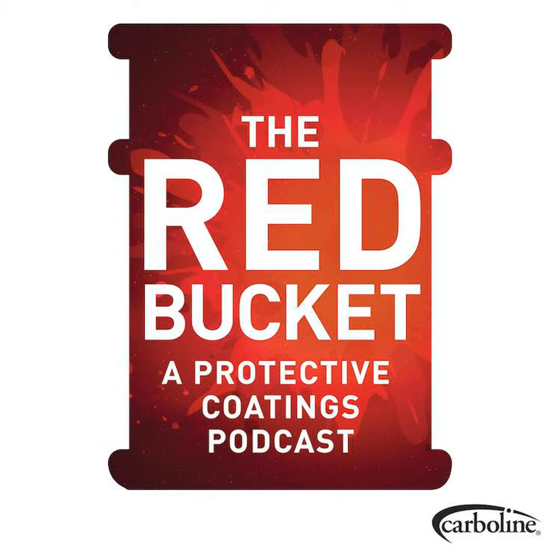Right. The urethane cements, I think I've said it on this show before, but I've definitely said it in the concrete presentations that I give frequently, is that a different guy that I knew who had been in the resinous flooring world for years used to always say, if you want to have problems, use epoxy. If you want it to go smooth, use urethane cement. And that's not an indictment on epoxy, because epoxy is still the most widely used coating material for concrete, and it is great. But when you get into these high moisture vapor situations, you really need to be using specialty epoxies if you're going to be using epoxies.